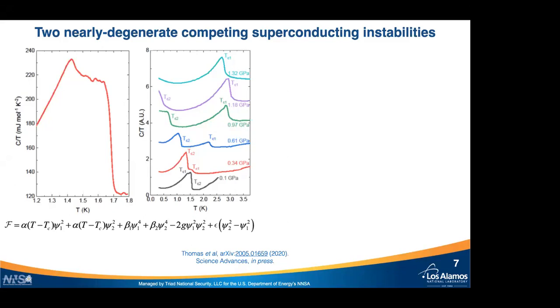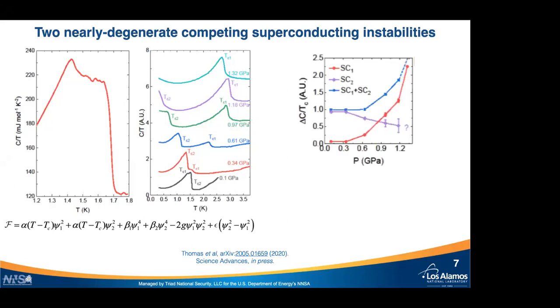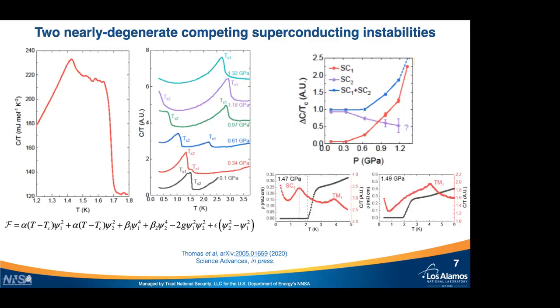From this simple free energy, we can conclude that the sum of the jumps at the superconducting transition temperatures has to be constant. You can see in this plot, the blue squares, that this is correct for low pressures. At higher pressures, this doesn't hold anymore, and that's likely due to the fact that we're going towards a magnetic instability. In fact, at 1.47 GPa, we can see another peak coming up. So we have superconductivity and a second peak above it, which is most likely due to magnetism, even though we don't yet have magnetic diffraction data on these samples. It's ongoing, underway, but we don't have that confirmation. But let's assume for now it is a magnetically ordered state.